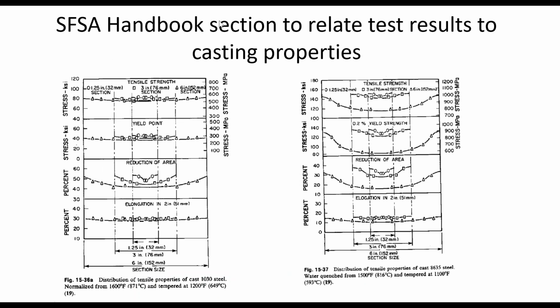So this is what that section looks like, and there are a number of things that show how the section size affects the properties. So in a cast carbon steel, the yield strength is around 40 KSI, which means that, for example, in the boiler code, you use 20 KSI.